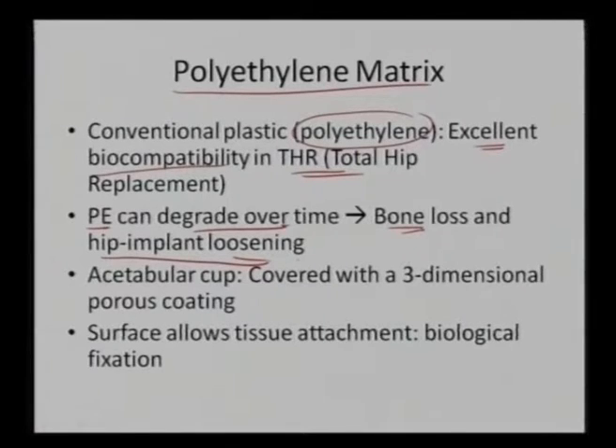Generally, when we have ceramic balls and a polymer liner, it will always lead to much more degradation of the polymer coating. So if you want to improve the wear resistance or the tribological properties of this polyethylene, we always need to incorporate certain ceramics as a reinforcement. In this particular case, we may also want to create a porous coating so that cells can come and adhere, or depending on the kind of applicability, we can also provide some lubrication in the porous coating. So that is the deal with this particular polyethylene matrix.